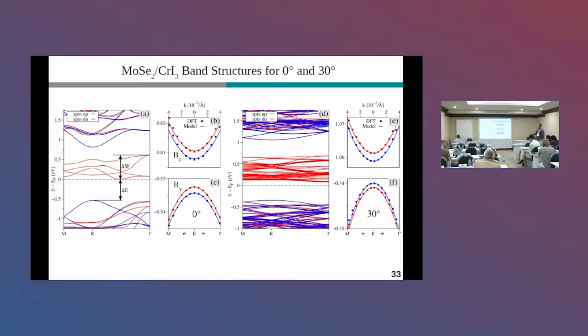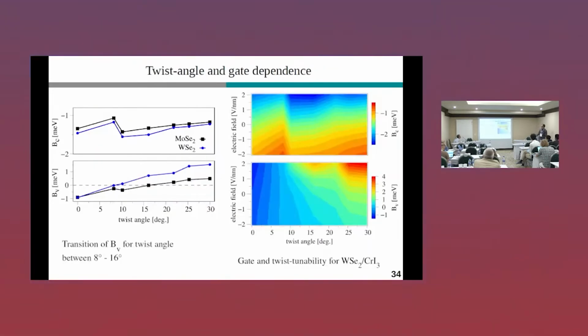Now, if you zoom into the band edges, you will find a splitting of the conduction band edge and the valence band edge like this. The spin ordering is the same, and we characterize the splitting by parameters BC and BV. If you then go to the 30-degree case, you find that the conduction band splitting remains, the spin ordering remains, while the valence band switches sign. So we can reverse the proximity exchange splitting in the valence band, which is similar to what we have seen before. And again, we did the full twist angle and gate scan. The conduction band splitting stays more or less the same upon twisting, but the valence band splitting can be very nicely tuned from negative to positive in a linear fashion by twisting from 0 to 30 degrees.